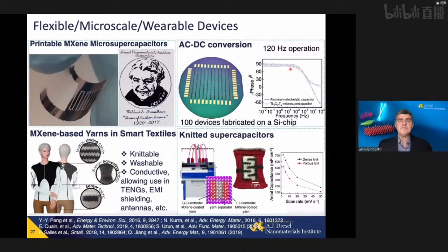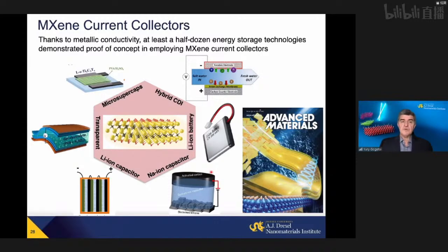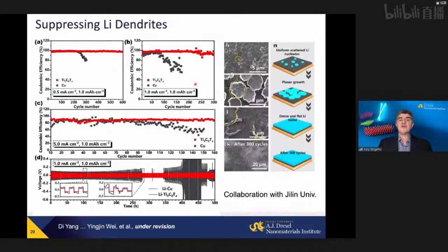But what is also important, whenever we have new materials, we need to think where they can make real impact and difference. And if we talk about two-dimensional materials, nanomaterials, naturally those are flexible devices, printable devices, on-chip, or wearable devices here. This is where you need to consider those materials. And if you talk about this type of transparent conducting films, for example, to replace ITO, used as current collector or battery electrode, you also can think about extra benefits. For example, suppression of lithium dendrites. And this is a paper with Professor Yinjin Wei and Alex Gao from Jilin University, showing stable cycling over 600 cycles of lithium and uniform film of lithium because of planar growth of lithium, not dendritic growth, on the surface of MXene here.